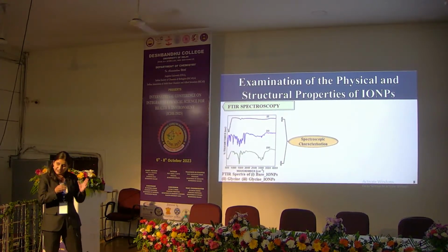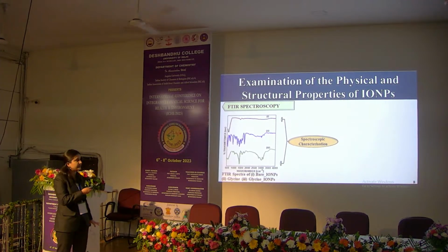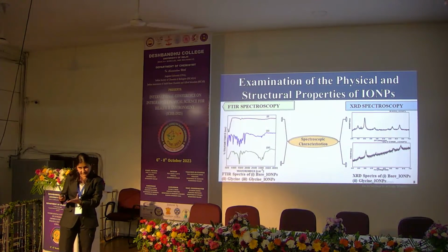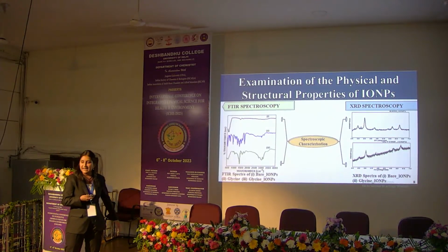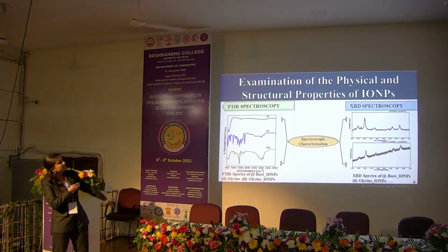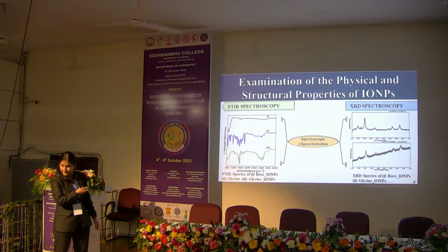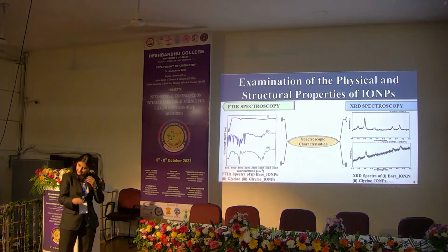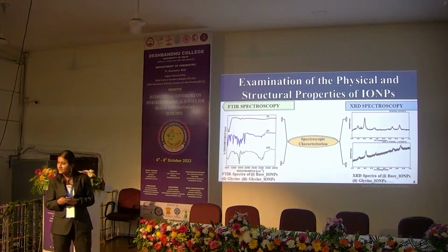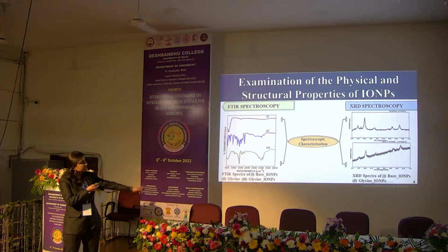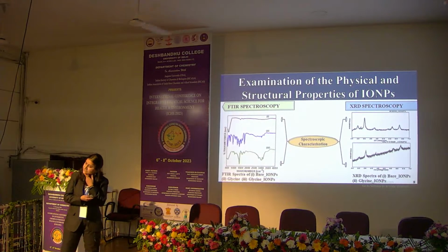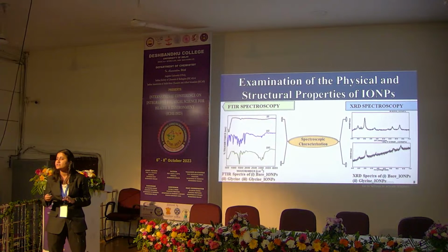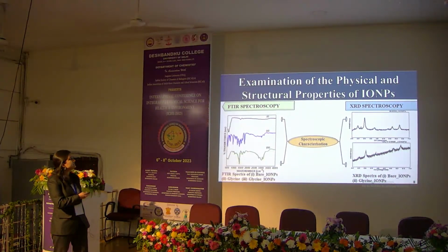This suggests that amino acids have been linked to the surface of iron oxide nanoparticles. Further, for the examination of the crystal structure of the nanoformulation, we have performed XRD analysis, and as we can see in the spectra, it contains 6 diffraction peaks which match well with the reported data values, and this further confirms the crystal structure of the nanoformulations. And we can see the XRD spectra of amino acid coated nanoformulations. It was observed that there is minimal impact of coating material on the crystal structure of nanoformulations.